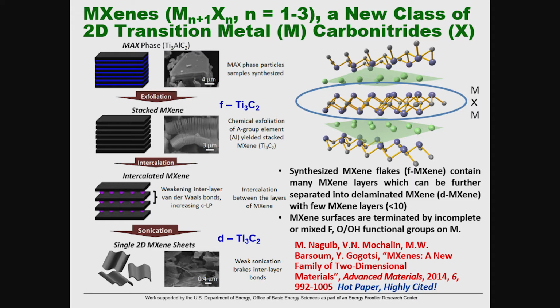Michael Naguib is here at this conference. He did his PhD work at Drexel developing these new two-dimensional materials that are kind of like graphene, kind of like clay minerals, but they are transition metal carbides and nitrides, so early transition metal, carbon and nitrogen, and there are many solid solutions here. You produce them by stripping the A out of a MAX phase. It's a layered three-dimensional structure that produces these nice flaky layers that look a lot like graphene, and in fact can be semiconducting, conducting, or insulating.